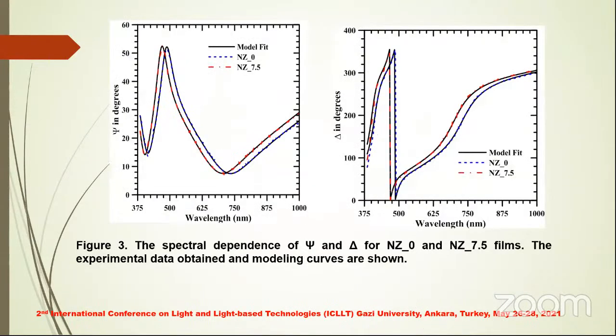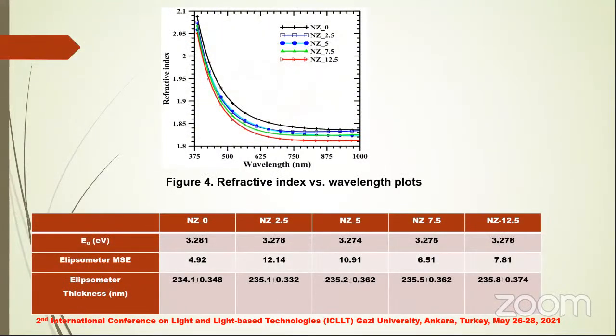In this study, the Cauchy model was selected as the model for zinc oxide thin films. Fitting was performed to ensure agreement between the experimentally obtained psi values and theoretically determined psi values using the Cauchy model. The variation of refractive index on the silicon substrate is shown in figure 4. As a result, the refractive index was found for each film, and it was observed that the refractive index decreased as the nitrogen ratio increased.